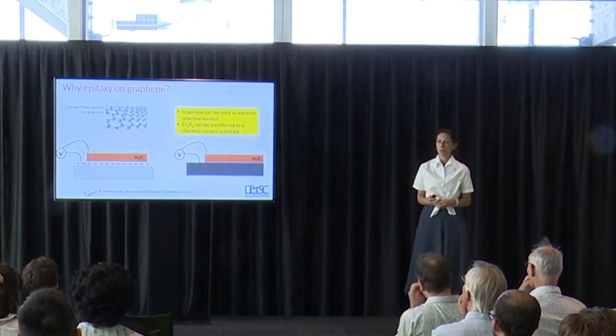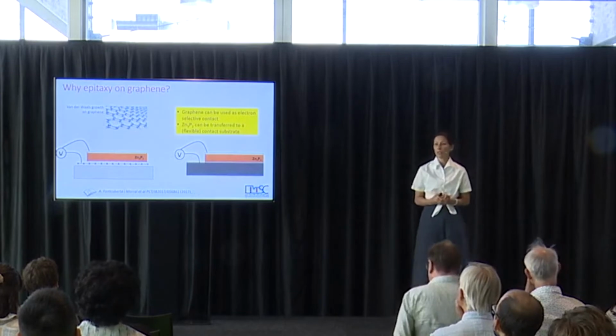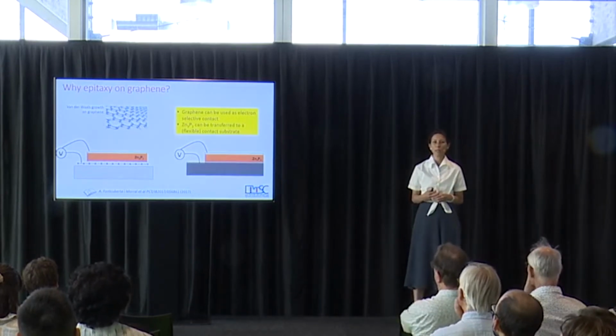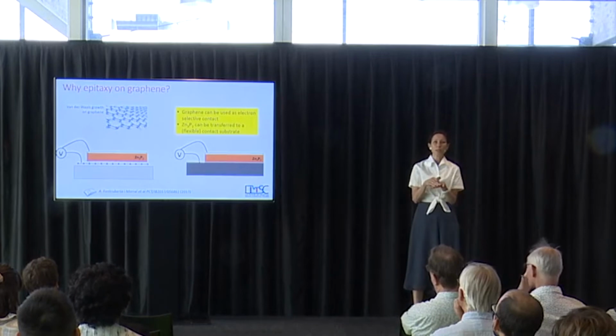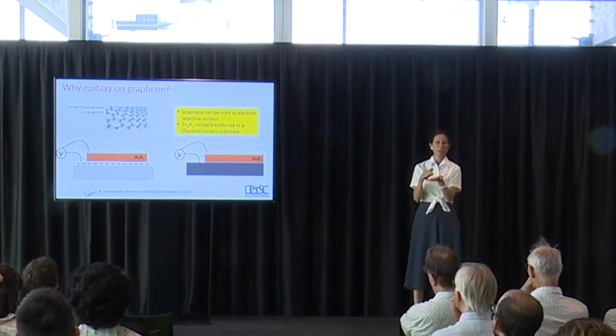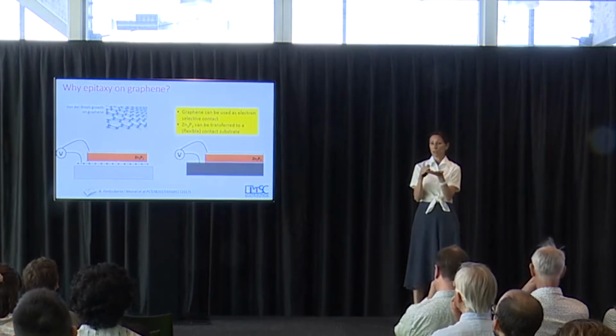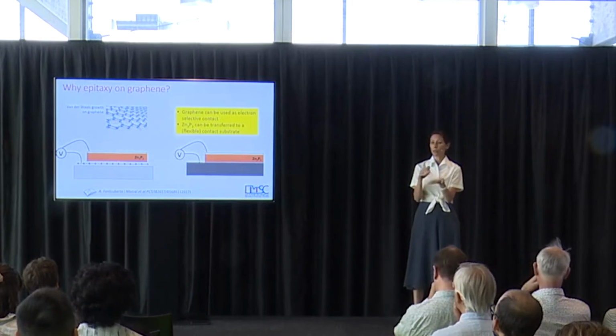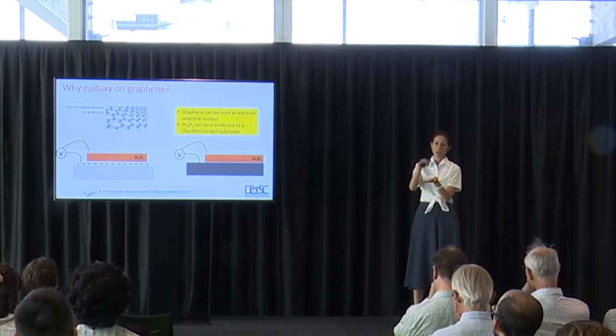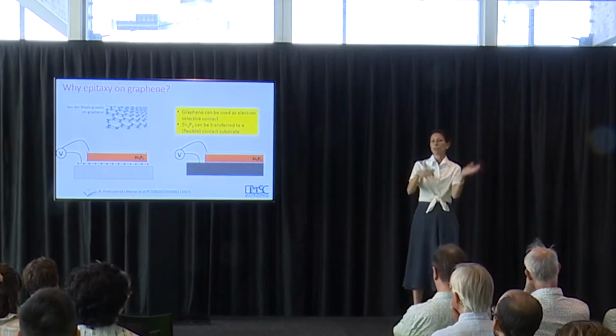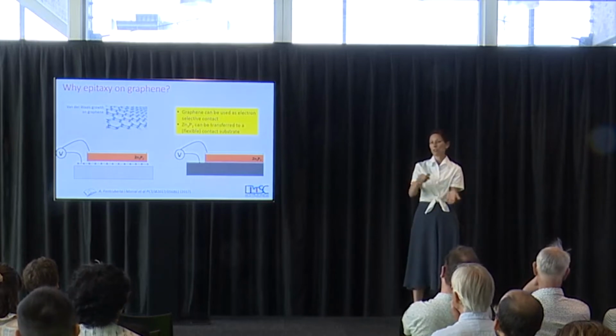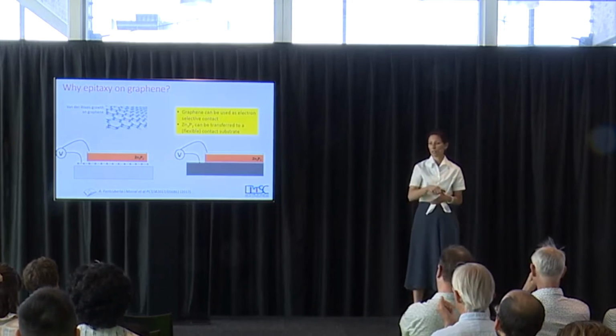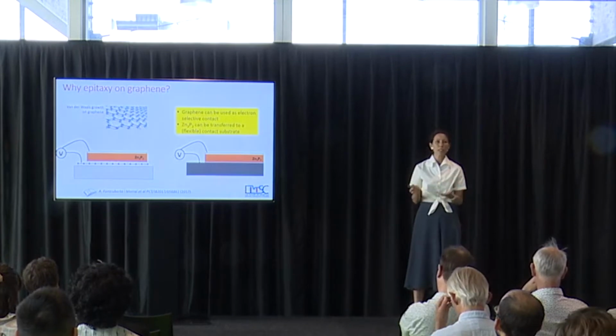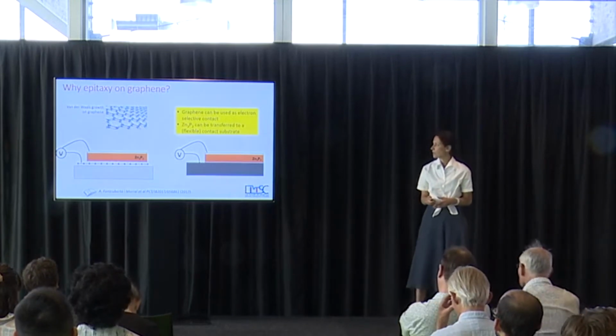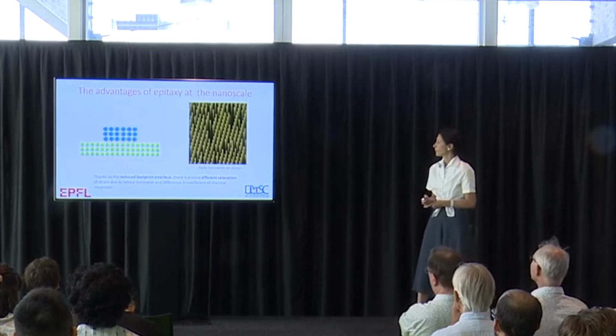Now why is this good? Having graphene helps the epitaxy, but it may also help in making some devices. First, you can have your device on graphene, and because graphene is conducting, even though it's not covalently bound with your material, there is a very good conduction, so you can use the graphene as a back contact, and then you just need to put the top one. Or, because it doesn't stick, you can just transfer your layers onto some other substrate and create your device. So it's also very easy to manipulate and to use to make devices. That's one of the reasons also to grow on graphene.